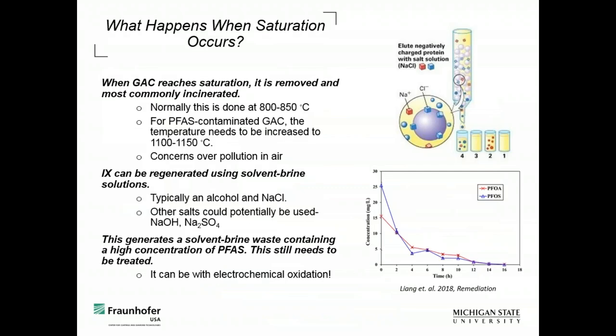So like I said, what happens when saturation occurs? For GAC, you take it out and you burn it and you incinerate it. And typically that's done at 850 degrees C for normal saturated activated carbon. But for PFAS contaminated GAC, you've got to jack that up a few 100 degrees C extra.